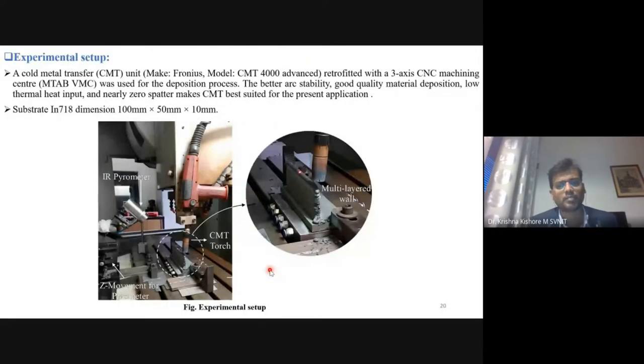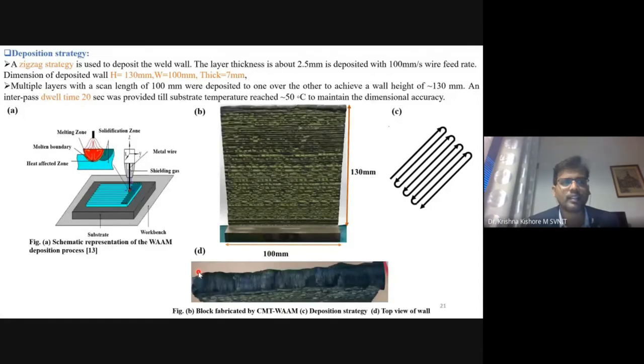And this is a simple experimental setup that we have used. On the CNC head, we have attached the cold metal transfer electrode head, or CMT torch head, and it has been mounted on a simple conventional CNC milling machine, right? So the movement of the torch is controlled by the CNC programming, and it is simple programming to go straight and come backward. But later on, we developed some codes to move in a weaving bead and other beads, right?